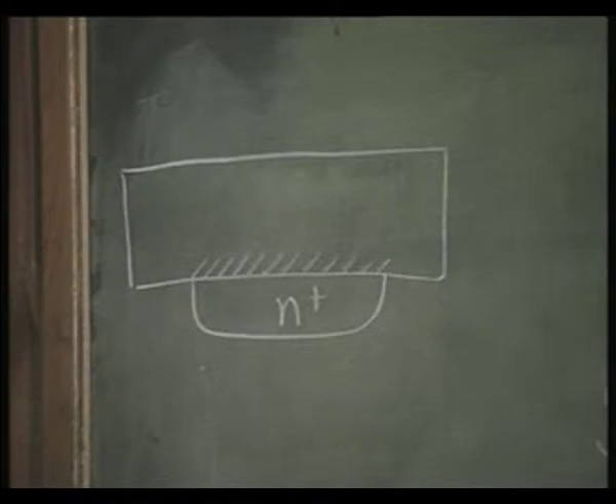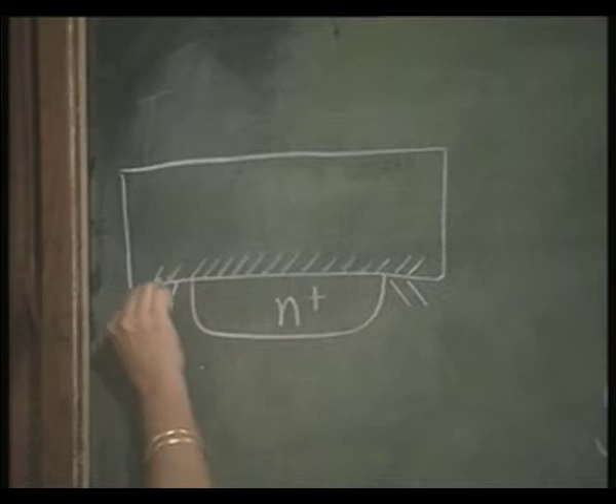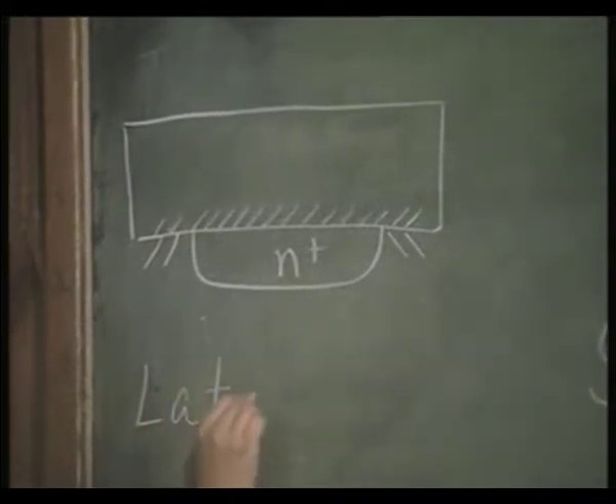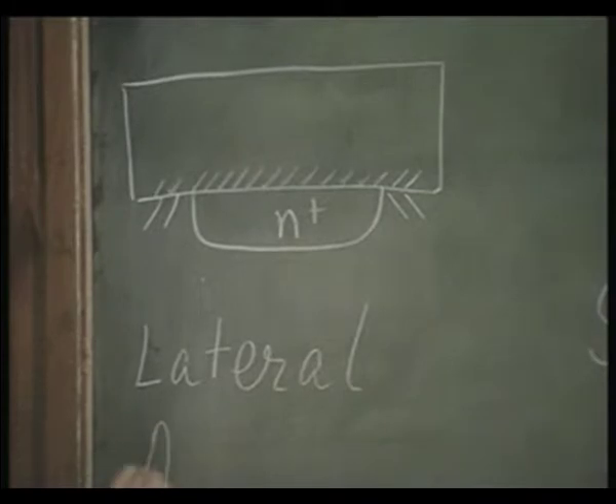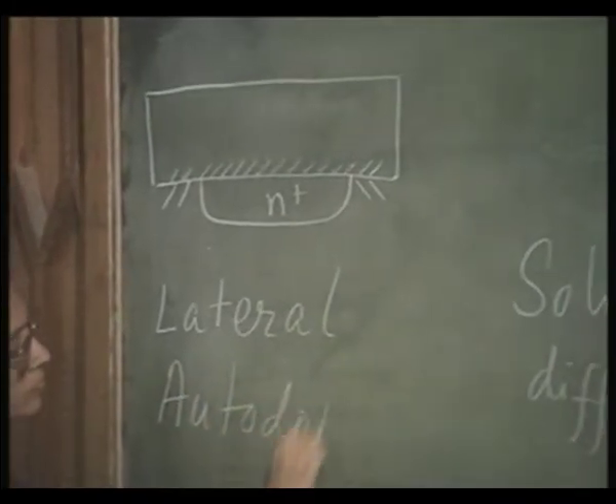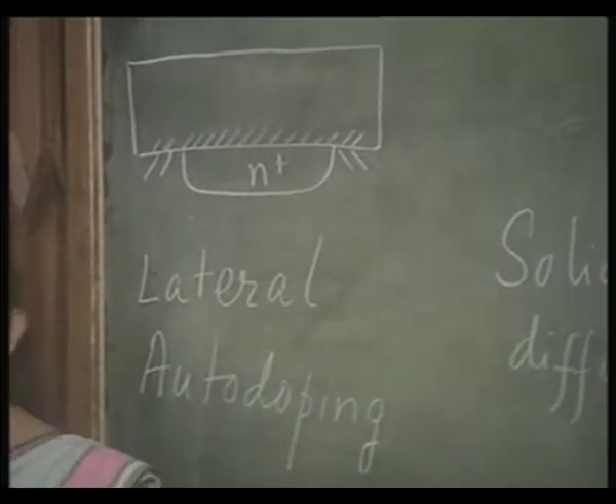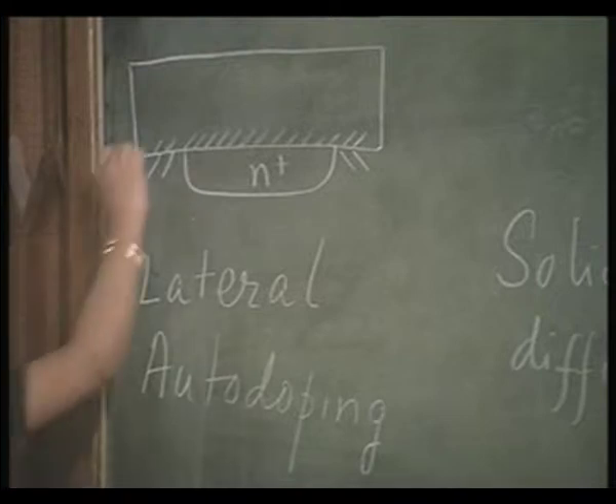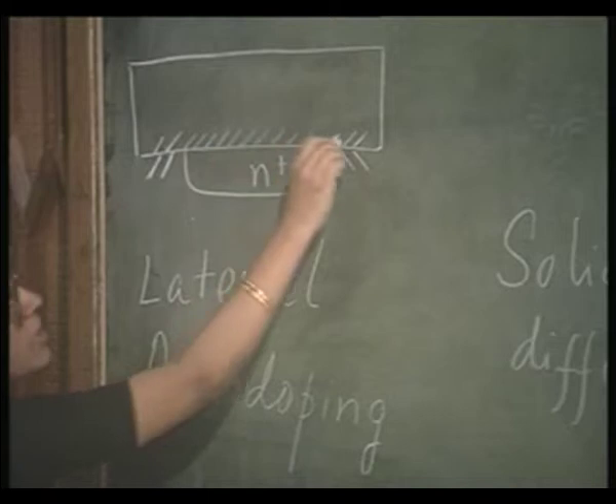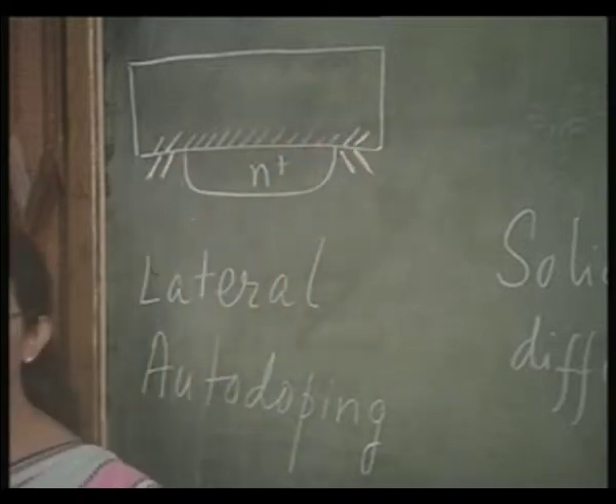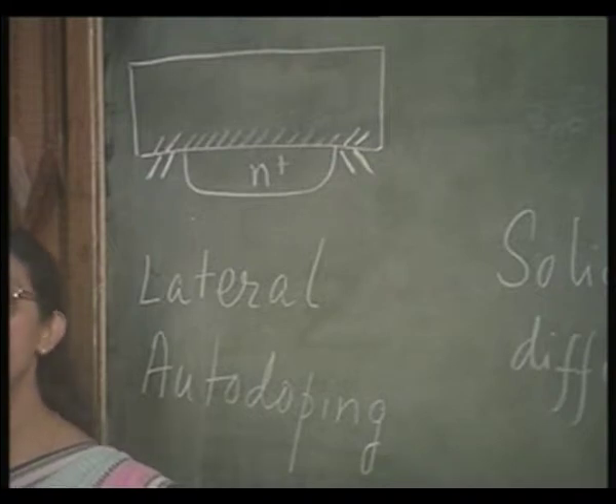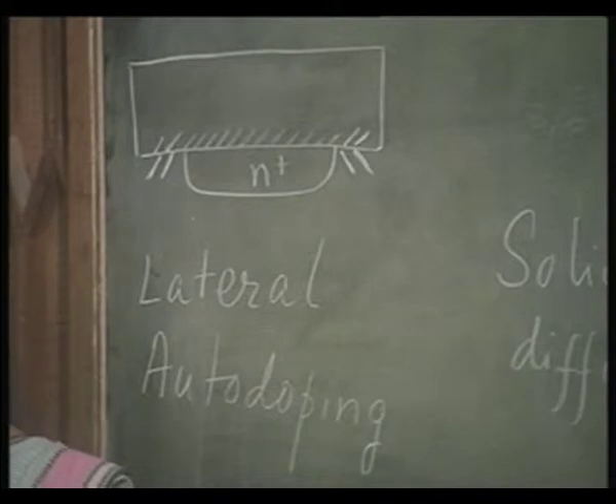This is vertical auto-doping, but actually the effect will also be felt to a region adjacent to the substrate. Okay. In fact, all over here the doping concentration will get modulated. This is called lateral autodoping. Lateral autodoping is almost exclusively due to gas phase autodoping. The solid state out diffusion plays very little role here. It is almost exclusively the effect of gas phase autodoping.